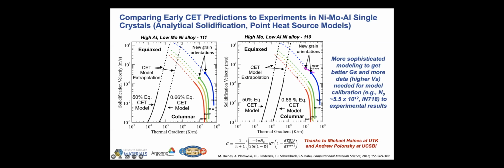And then also these analytical types of models have some fudge factors built in them. For example, this N0 is nucleation site density. And here we're using an approximation available for Inconel 718 from the work of Andrew Polonsky at UCSB, but really this has to be calibrated for different alloy systems. So there's a lot to go into to start becoming predictive.